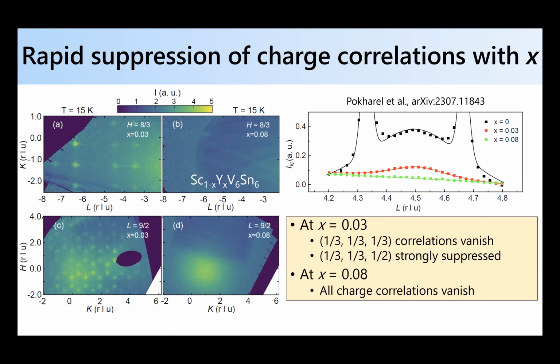We can do X-ray scattering and show that more directly. And one can show here at the 3% sample, you have only these third, a half short-range correlations that survive. There's no more long-range charge order. And then at the 8% sample, all charge correlations have vanished.